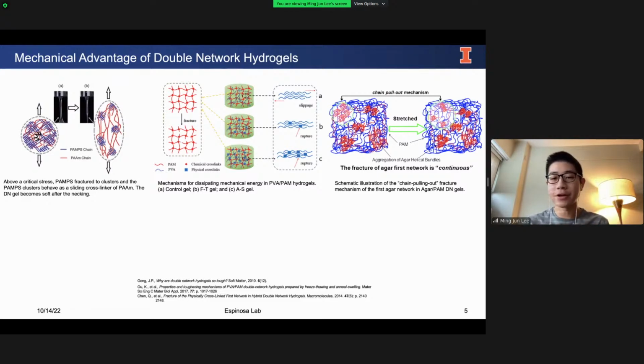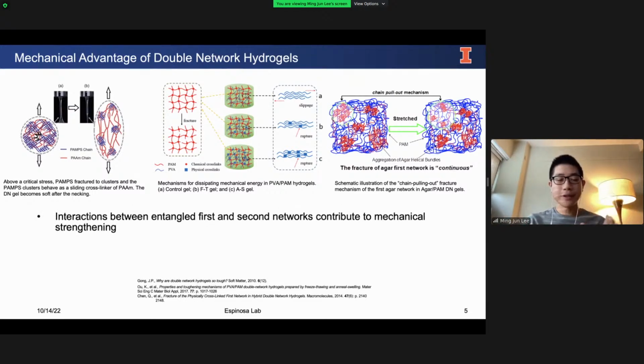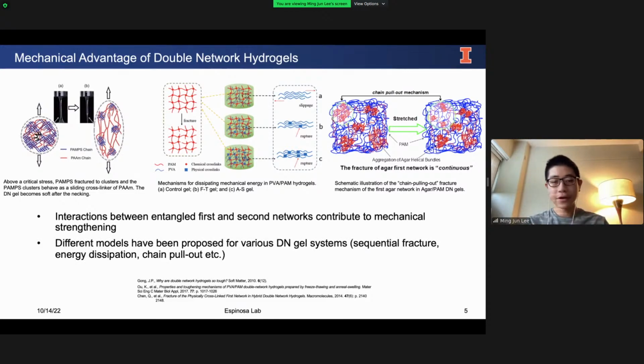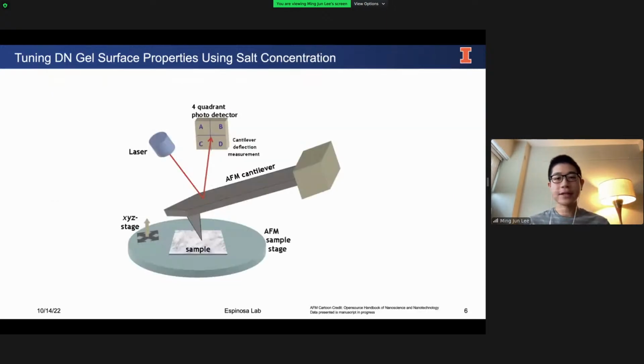Here I'm showing three different diagrams from three different papers. They are explaining the mechanisms of energy dissipation in the double network hydrogel microstructure. But what I want to highlight is that all these mechanisms have one thing in common, and that is the entanglement between first and second networks. So if we imagine a fishing net, where the horizontal strings are the first network and the vertical strings are the second network, this kind of entanglement between the two networks naturally leads to an enhancement in mechanical properties. Different models have been proposed, but they all have this one thing in common. And that's why I think double network hydrogels are suitable for synthetic replacements, at least in the mechanical space.